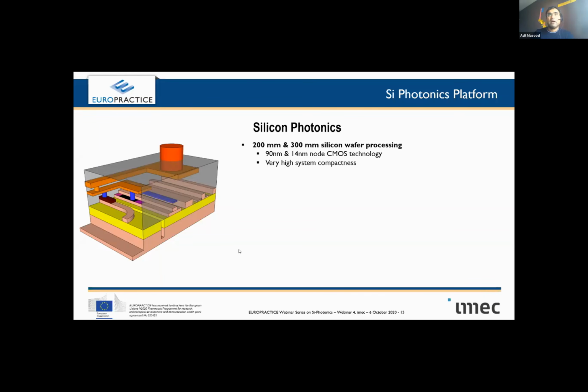Now, a quick highlight of the silicon photonics platform. At imec, silicon photonics is fabricated on 200 millimeter as well as 300 millimeter silicon wafers. And the two technology nodes which are used respectively are 90 nanometer, and in the case of 300 millimeter, it goes down to 14 nanometer node. With imec, what is offered through MPW is only 200 mm wafer-based technology, which means on 90 nanometer node, and it's called iSiPP50G, where iSiPP stands for imec Silicon Photonics Platform with a 50 gigahertz targeted modulation. And iSiPP200 does not mean 200 gigahertz, but it means a lot more dedicated wafer, dedicated fabrication offering.